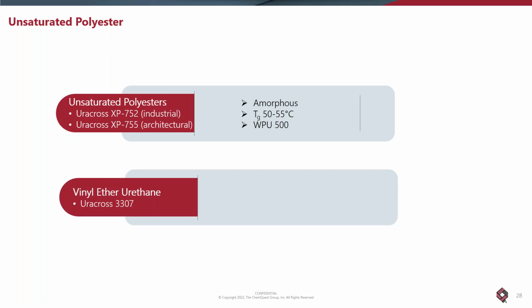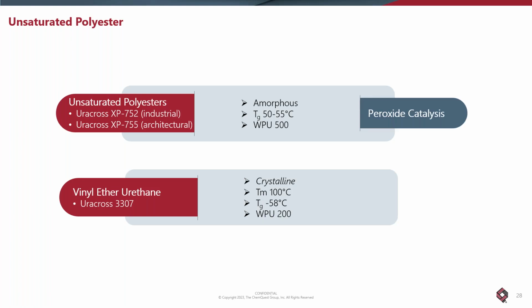You cure that with a vinyl ether urethane, which gives you a really nice cross-link density. This vinyl ether urethane is also a relatively crystalline material, and it gives you the opportunity to make a nice thermoset system that you can use a peroxide catalysis system and kind of make this thing work. It's been available for probably about 15, 20 years, believe it or not. It's some pretty interesting and, I would say, non-traditional chemistry for the powder coating world.